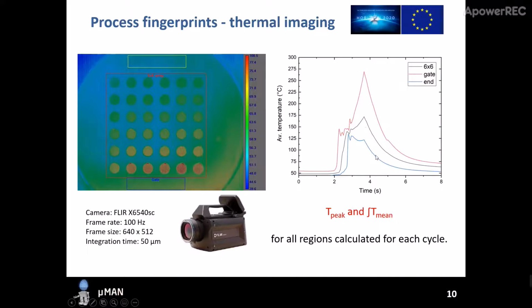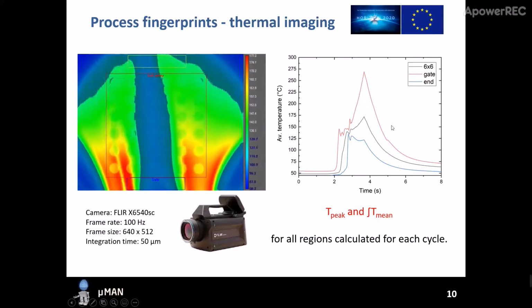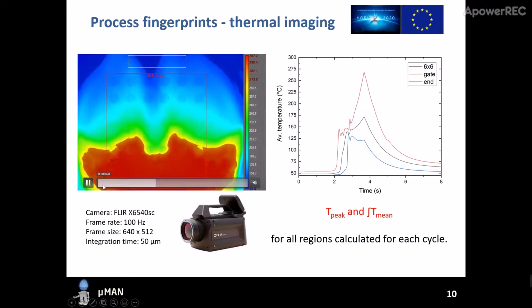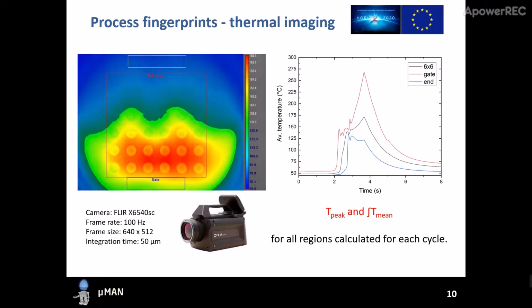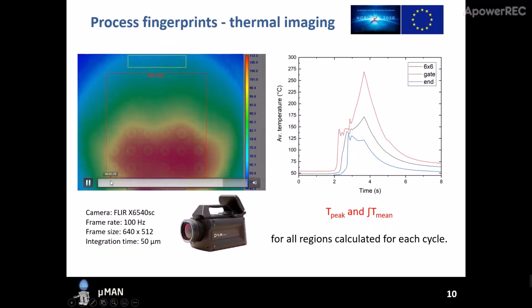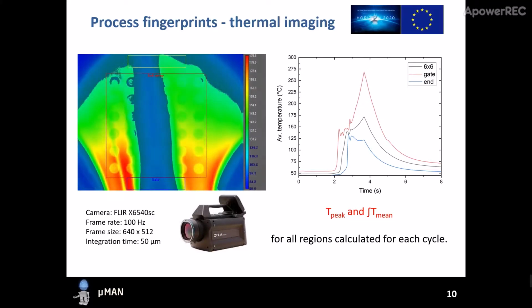These are the average or mean temperatures within those regions of interest, and today we will be focusing on the blue curve and the black curve, which are the temperatures from the end of the cavity and from the 6x6 microneedle array. From these two curves we extract peak temperatures and temperature integrals, which is the area under the curve, and these are process fingerprints from thermal imaging. This is how the ultrasonic micromolding is carried out, and we capture all the temperatures from pixels at 100 Hertz. If I can play this again, it will be better seen.